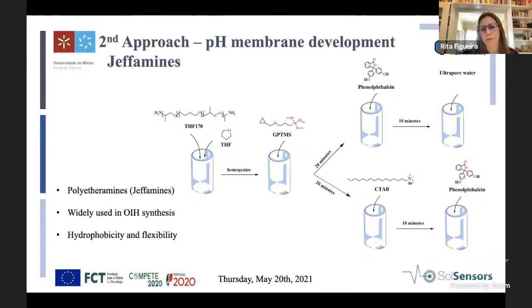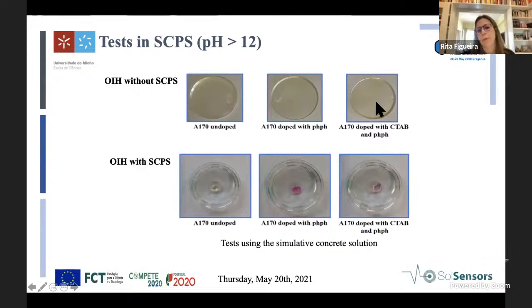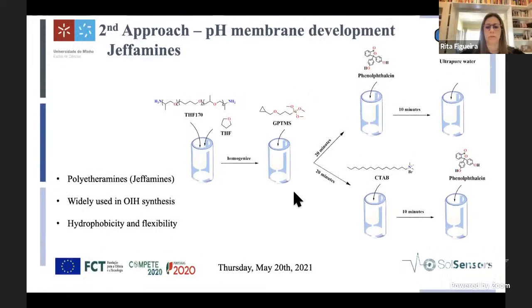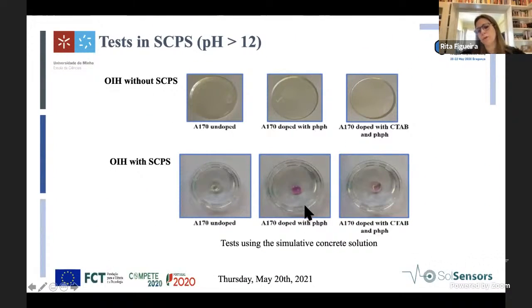The second approach included using phenolphthalein in the matrix already reported, and we used CTAB. We prepared the synthesis with CTAB and without CTAB. You can see here the samples prepared, without being in contact with the simulated concrete pore solution at pH above 12, and here after being in contact with the simulated concrete pore solution. As you can see, the undoped film does not show any change. The film doped with phenolphthalein shows changes when in contact with the simulated concrete pore solution, either with or without CTAB.